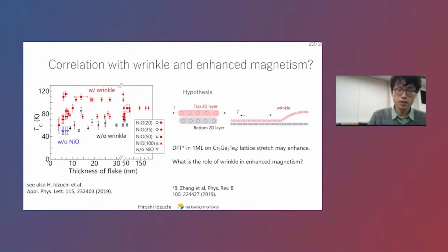it seems the formation of this wrinkle is somewhat correlated with enhancement of Curie temperature. And there is a story on DFT calculation, so that this indicates lattice stretch may enhance the magnetism. So our hypothesis is here. If we have two layers, somehow if we can stretch, the top layer can have wrinkle. Suppose the number of atoms is conserved. So if this area is stretched, somehow this area needs to have wrinkle.